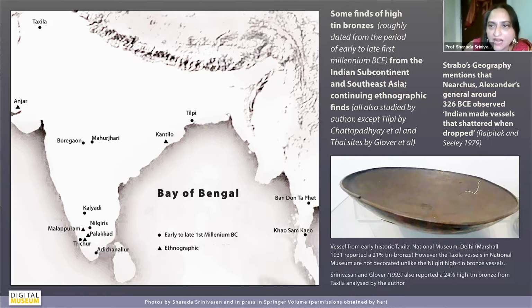In fact, that was how I came to think about looking for ethnographic practices of high-tin bronze working in the Indian subcontinent, because before I identified those, there was no parallel of ethnographic studies of high-tin bronzes, certainly in the Indian subcontinent. It was because my grandmother, when I was talking to her, mentioned these Ottupathram and the Thalavettu and so on, which were still made in Kerala, and which they had to be careful not to drop because they broke like pottery. That's exactly what she said, which was so similar to the account in Strabo's Geography.